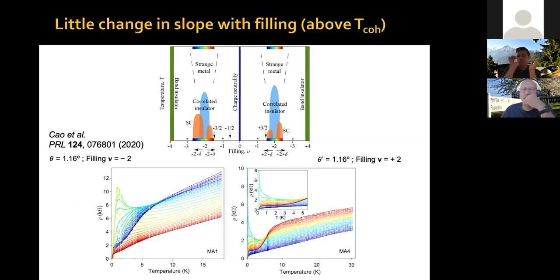So basically, for a very high quality device, the Shubnikov-de Haas oscillations are very sharp, so you determine the maxima very accurately, and you can extrapolate those lines very accurately. When you have a more disordered device, then those Shubnikov-de Haas oscillations are broader. You can determine them less accurately, and you can determine the extrapolation to the density for the correlated insulator state more poorly. So we estimate how good our extrapolation is based on our fitting procedure, and that leads to the error bar in the twist angle that I have mentioned in some of the transport data.